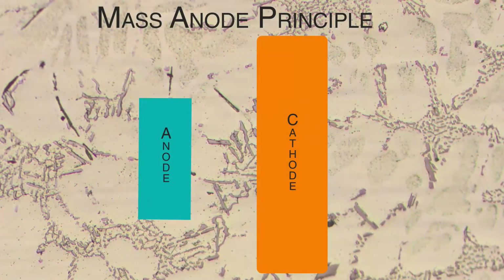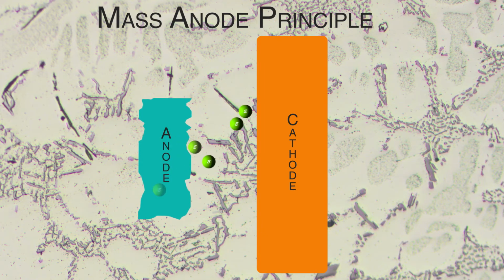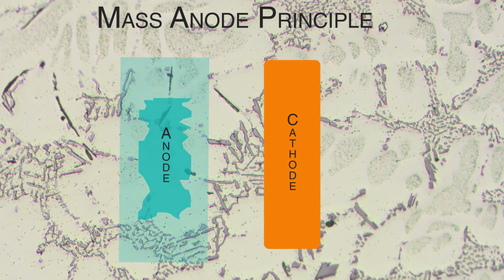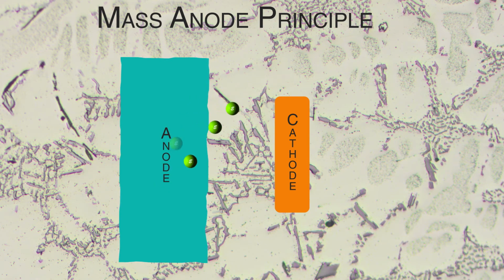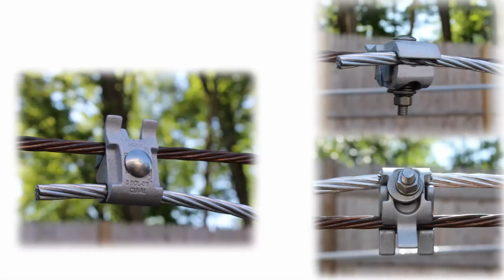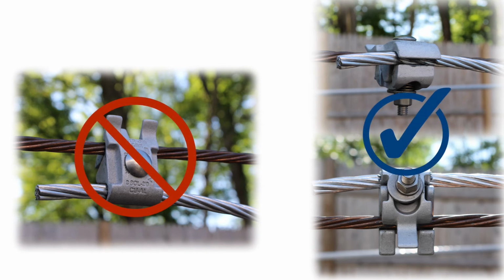And the last one that is often used, and this is why we recommend using aluminum for an aluminum to copper, is using a principle called the mass anode principle, where if your anode is significantly more massive than the cathode, the rate of corrosion is significantly reduced, so that it basically reduces the amount of corrosion over the life of the connection. There's a term in the industry called know your ABCs, which means aluminum above copper. And basically what that means is whenever you have a bimetallic installation and it is going to be exposed to the elements, you want to keep your aluminum above the copper, so that if a galvanic cell is created, the cell is beneath the aluminum conductor, and the mass anode principle will take effect and reduce the galvanic cell in the bottom part of the connection.